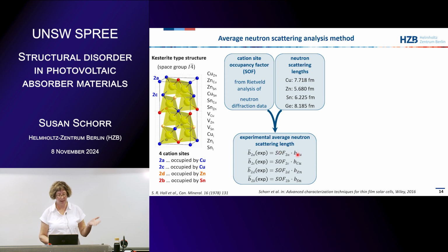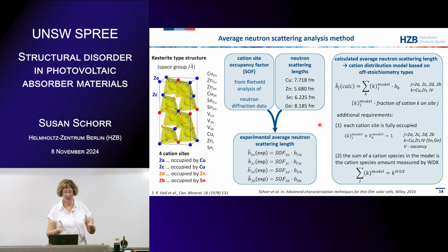So if there is only copper, then the site occupancy factor will be 1. If there is a copper vacancy, there is nothing to scatter, and then your site occupancy factor will be below 1. If there is zinc on copper, your site occupancy factor will also be below 1, because the neutron scattering length of zinc is smaller than that of copper. So that means the site occupancy factors will all differ from 1 because of the defects we have here. So this is the experimental side.